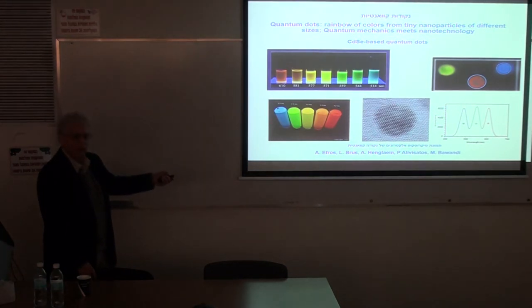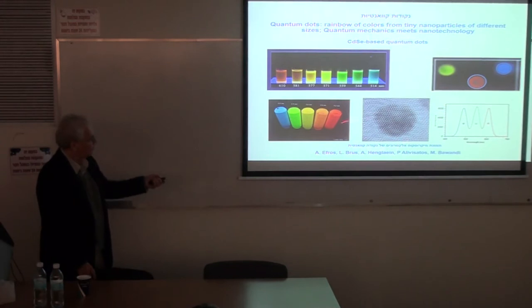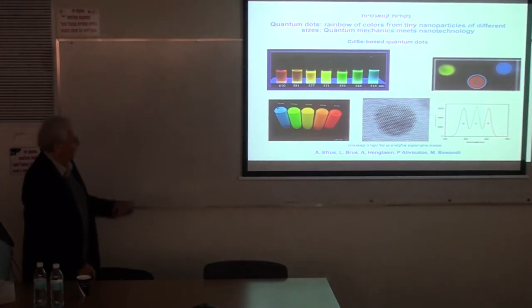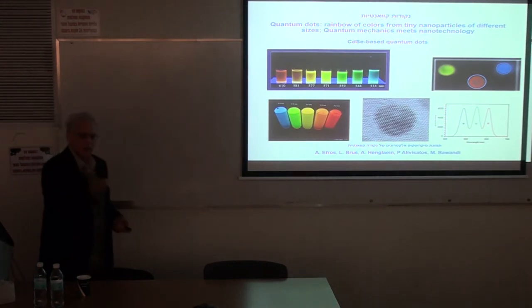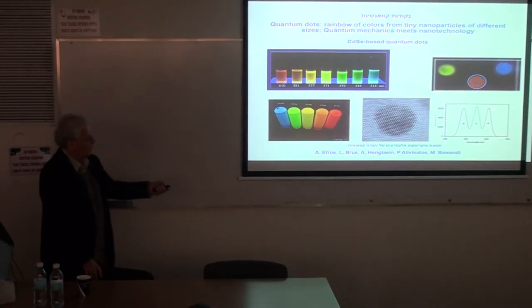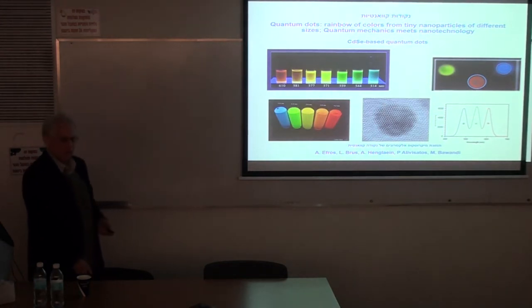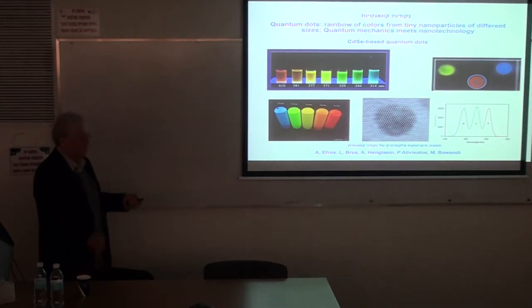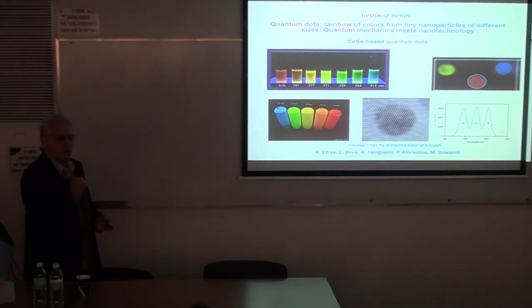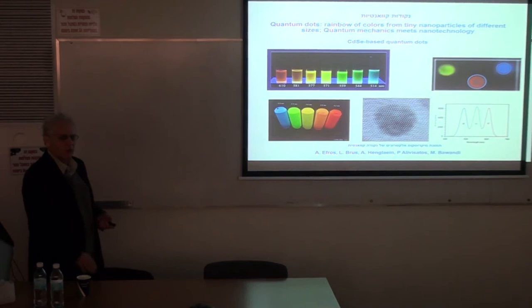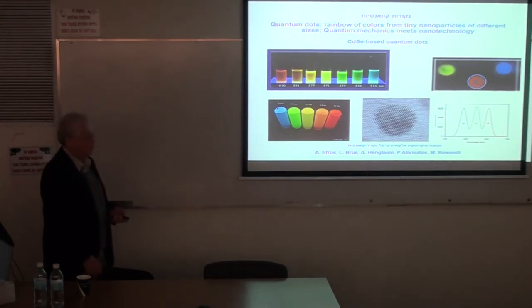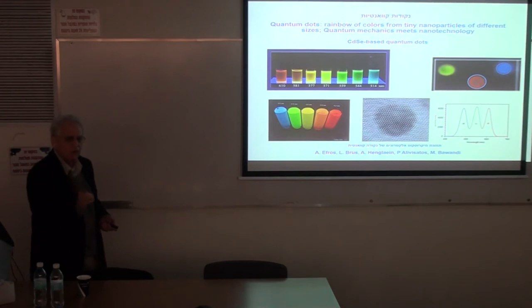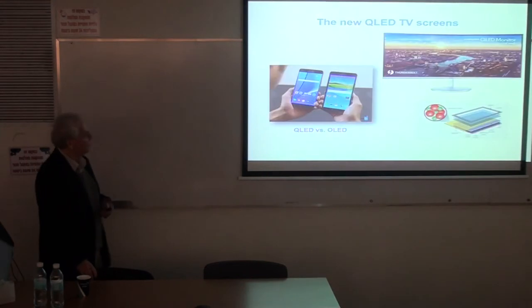And you can see with a spherical aberration corrected TEM, you can see beautifully the structure of one single quantum dot, and you can calculate by Schrödinger equation, by DFT, the spectrum of this quantum dot, and you can superimpose it on the experimental one. And you can see that each quantum dot will give you the same, or almost the same, because the control on the size distribution is so good, plus minus 2% or 3%, that you can really control them all to give the same color. And this has an important technological ramification, which I'll show in the next slide.